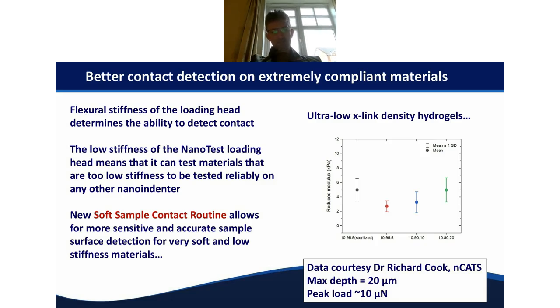So when we think of performing measurements on extremely low stiffness materials, this is quite a challenge for an indentation system, because when you detect contact, you have to have something that says, right, I've detected contact, now I can apply the load. So if you have a typically stiff loading head system in the direction of loading, then it's very, very difficult to detect that additional stiffness from the contact. So this flexural stiffness of the loading head determines the ability of the system to detect contact.